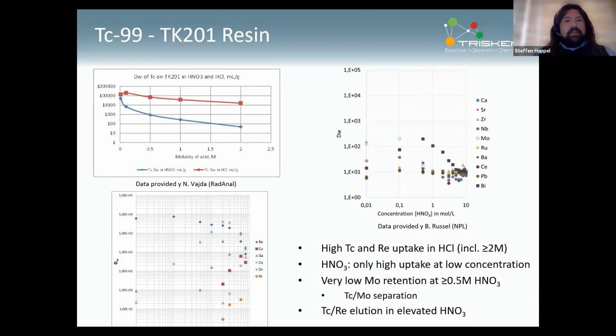What is a bit particular is that, especially also compared to TEVA, the retention in HCl is very, very high, even up to 2M HCl. So you can extract the technetium from quite high acid concentrations. It's not quite working as well for nitric acid, so you would tend to stay at about pH 1. On the other hand, you are getting into a region where you can start looking to elution of the technetium, something like 3 molar, which is a bit lower than for the TEVA resin, for example. Here also, the rhenium is following the technetium quite closely. So you can use it as a proxy for the technetium.